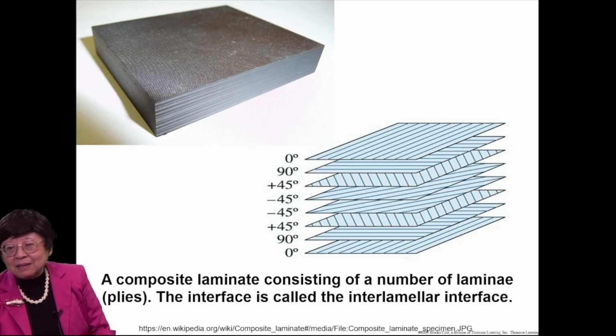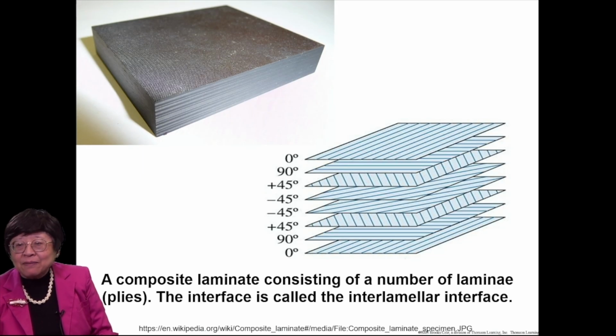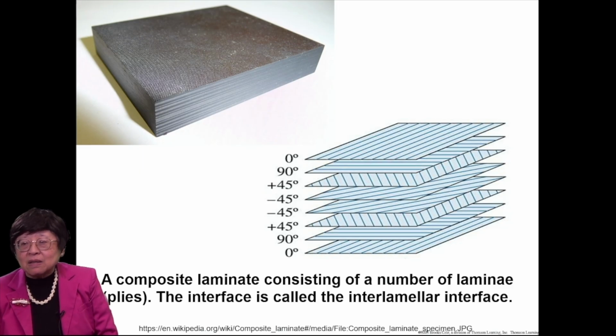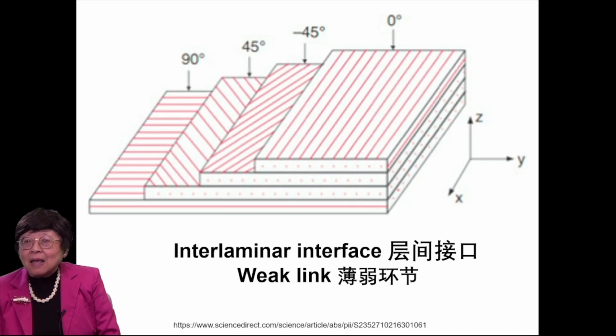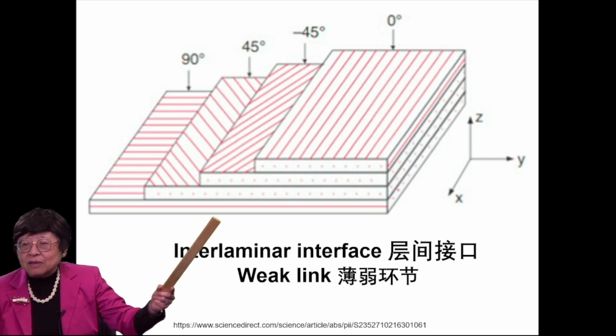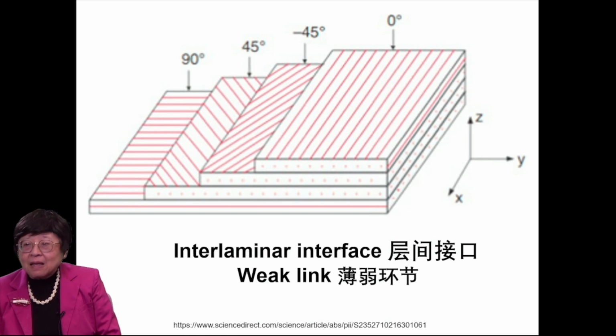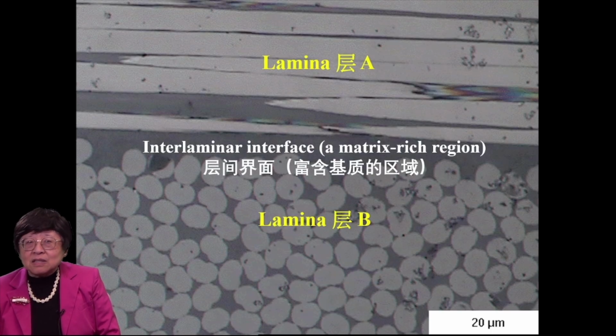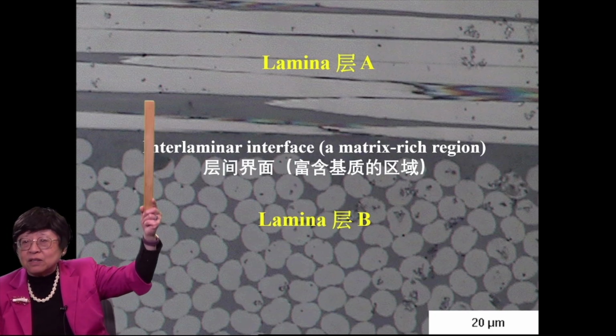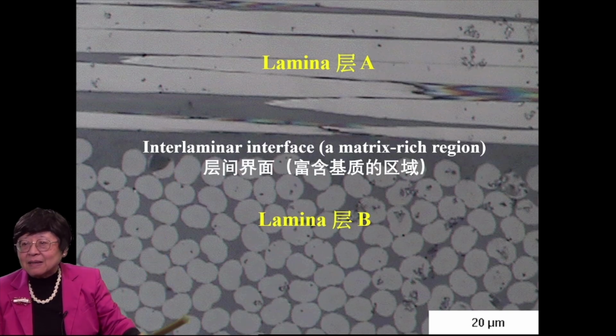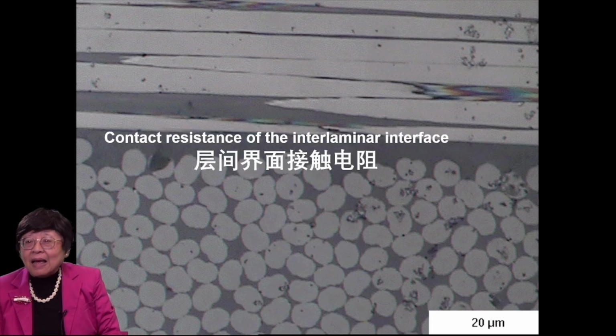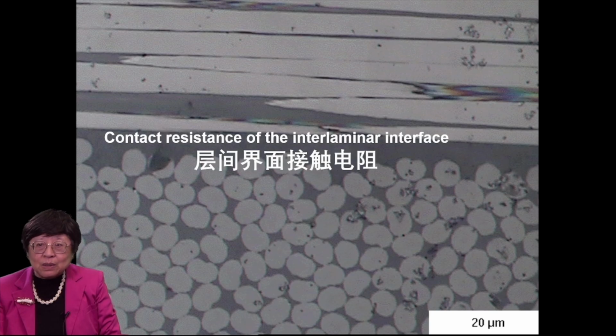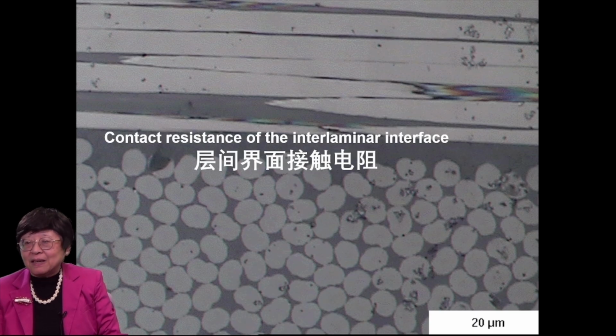A composite laminate consists of a number of laminae or plies, and the interface between the plies is called the interlaminar interface. This interface is the weak link. This is a microscope view of such an interface between two laminae, A and B. The interface is a matrix-rich region, and that is the weak link. If we can zoom in electrically at this weak link by measuring the contact resistance of this interface, one can monitor the condition very, very sensitively.